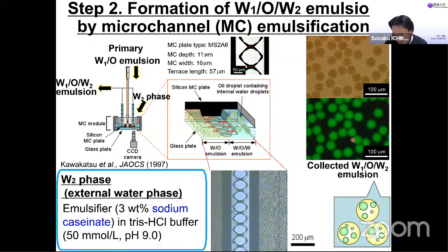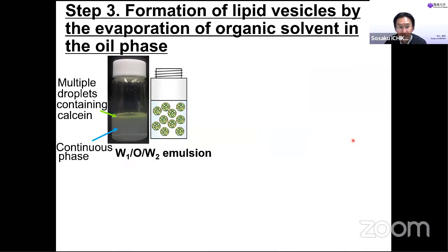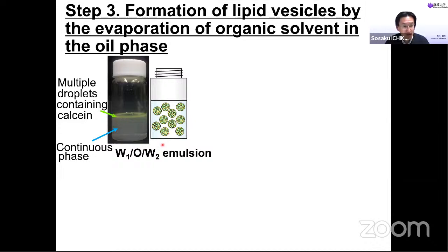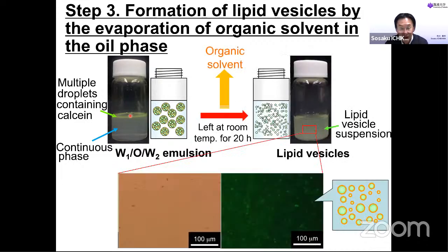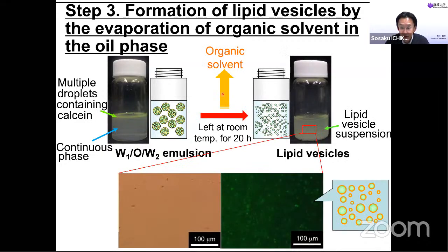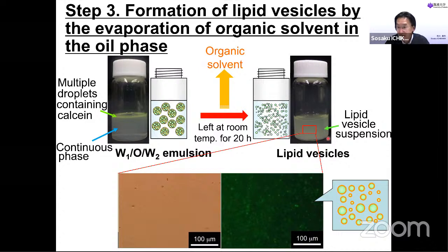From this W1/O/W2 emulsion, we evaporate organic solvent like this. This is the continuous phase. This is the oil droplet accumulated at the surface of the aqueous phase. After the organic solvent evaporation, we get this lipid vesicle suspension like this.